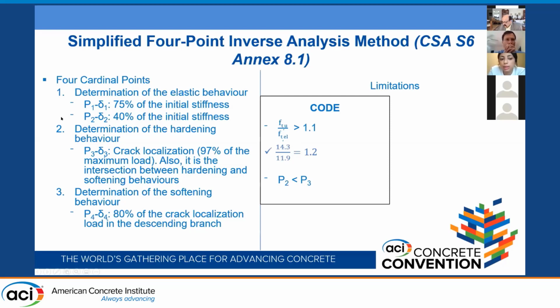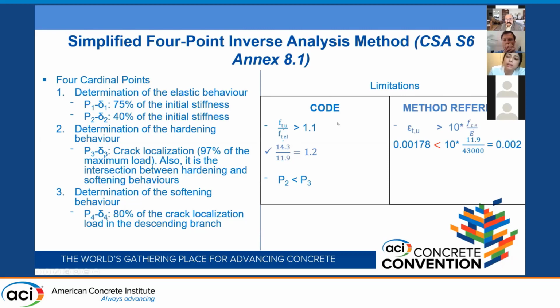And P2, as you can see here, which is the 40% of the initial stiffness, has to be less than P3, which is the crack localization point. Now the method, like the reference of this method, also imposes a third limitation, where the tensile ultimate strain has to be at least 10 times greater than the elastic tensile strain. Now this condition is not satisfied for the material I am using, as you can tell.